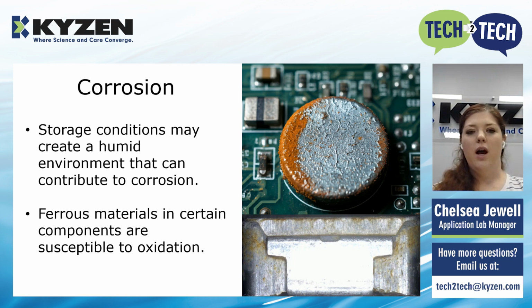The other issue is corrosion. It's fairly common that we see inductors or other materials that have ferrous components. When you combine any type of moisture and ferrous components exposed to that atmosphere, this corrosion can present. Storage conditions are a key factor in this. So if that board isn't completely dry, free of moisture, and cooled back to room temperature, if you're bringing them out and packaging them up, even so much as flipping the ESD bag over and putting a label on it, you can still create pretty much a humidity chamber inside that bag if there's any type of moisture present.